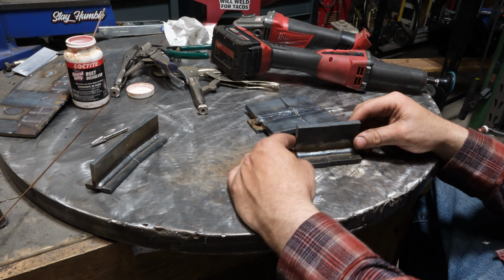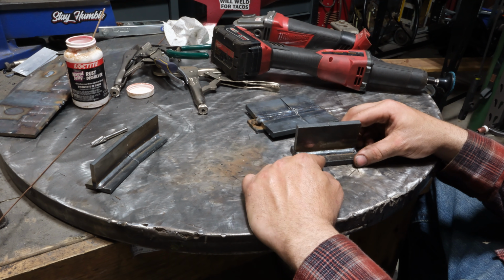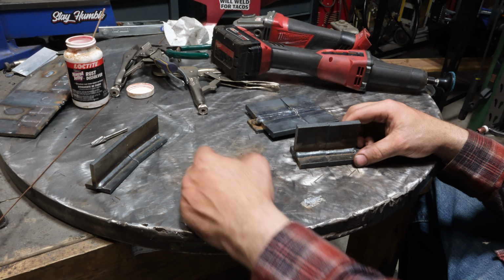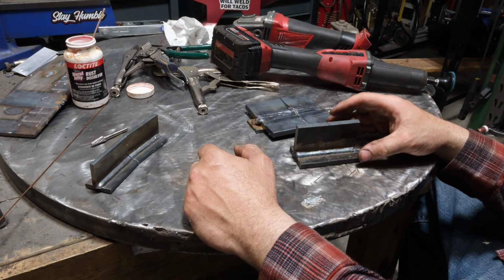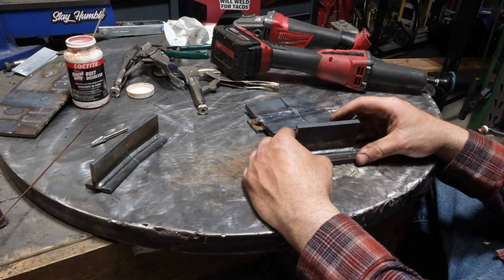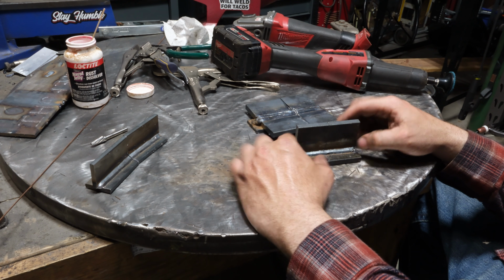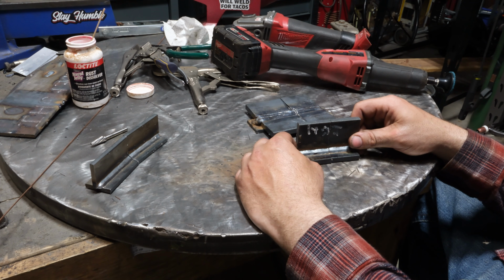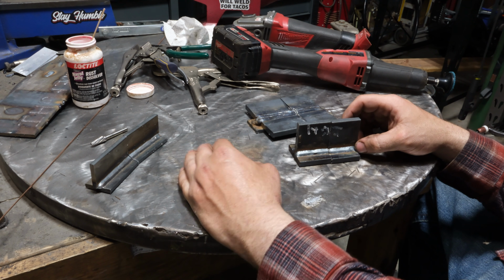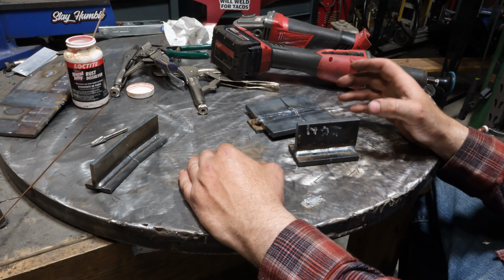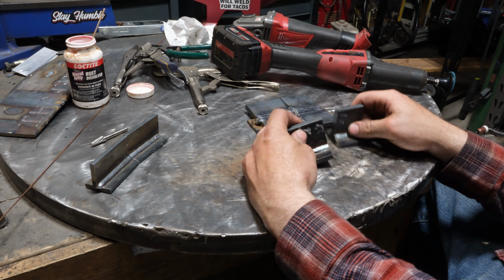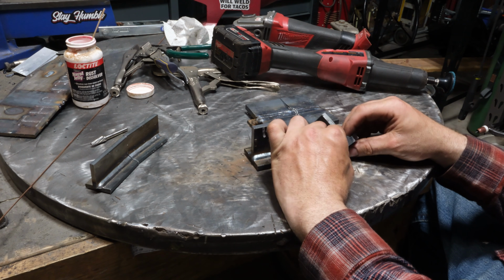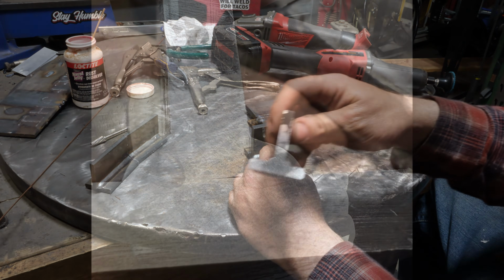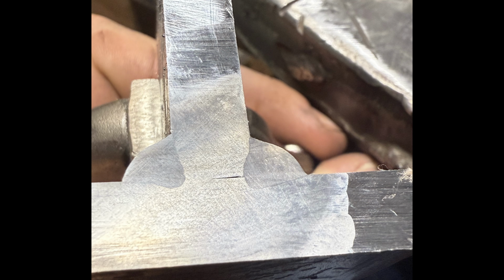So now let's take a look at this 3/8 plate. On this side, I ran the same settings as the 1/4 inch plate, which is basically 100% maxed out on a 200 amp machine. That would be the most you could get out of it. And I ran a pass, and then I ran it at what Miller Electric would suggest for 3/8, which was a significant bump up. I'll put the settings up when we look at both of them. But these actually surprised me a little bit, better than I expected. But let's take a look at it. So the weld on the left was done at reduced settings, the weld on the right was done at increased settings, and we'll look at what those settings are in a minute.